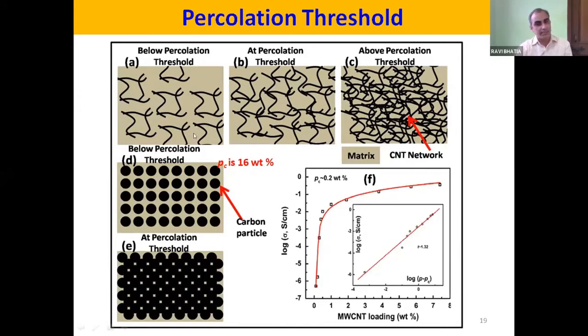However, in the case of quasi one-dimensional filler material, the situation is like this. Below the percolation threshold, there is hardly any connectivity between these thread-like particles, and at the percolation, they just get connected and they are homogeneously distributed. This is the most important condition to make a high-quality composite sample. And above the percolation, when you have already achieved percolation, it is going to saturate here. For example, please look at the F graph. As the MWCNT loading is increasing, there is an abrupt change of conductivity, or increase of conductivity, right here. So this region is called the percolation threshold region, where this part is called the saturation region.